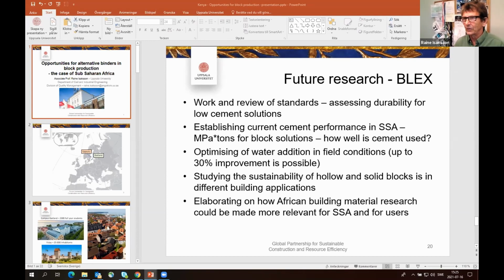And there are 2 things here with the future research. One is, what can we do with the blocks? I think still things could be done there. We could maybe improve the performance by 30 or even 50%, but that will not solve the big problem with the cement, as we saw, being produced in big factories normally costing something like $150 to $200 million. It happens in places in Tanzania that the cement is transported for 1,500 kilometers. We would instead need some alternative binders that can be produced in smaller local units that can perform well.